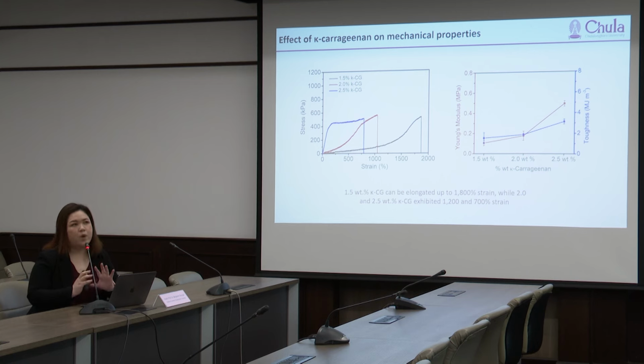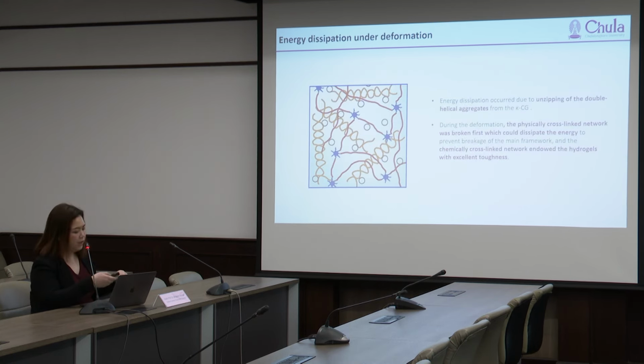So what happens when you apply force is that during the deformation, the physically cross-linked network from the unzipping of the double helical structure will be broken first, and then it can dissipate energy and prevent the breakage of the main framework from the chemical cross-linked network that endowed the hydrogels with excellent toughness.